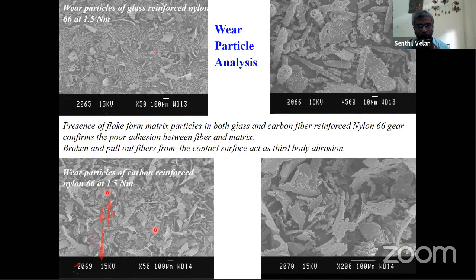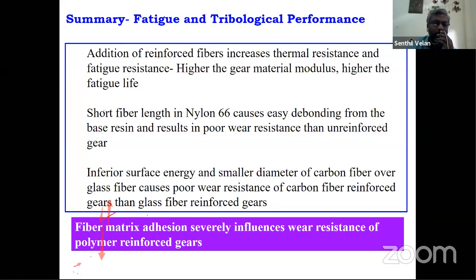This is the summary we wanted to present over here. So in tribology and fatigue, it is not just by adding some reinforced material that you will end up getting a better product. It is not so. We have to be more and more careful, particularly if it is a tribology application. Then we have to bother about the surface energy, the fiber diameter, fiber length, and number of ends. Everything matters. So this is what we have to be careful about in choosing the appropriate material for our application.